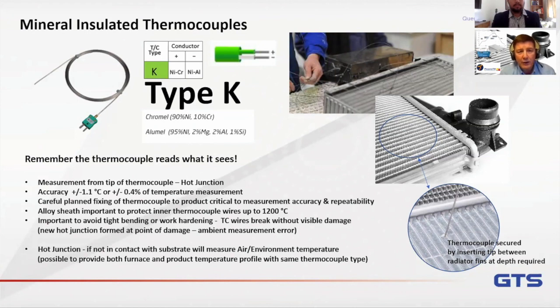Be careful though, because I've seen a lot of customers using these thermocouples and they look bulletproof, almost bomb-proof, and they think they can take them through fairly severe handling. Now, at the core of the mineral insulated thermocouple, there are two very thin wires which make up the dissimilar metals, the chromel and the alumel legs of the thermocouple. The outer sheath may not look as if it's damaged, but if you stress or strain that cable repeatedly or bend it round a very tight radius, you can physically snap the legs of the thermocouple internally. What that does is it creates what we call a new hot junction.